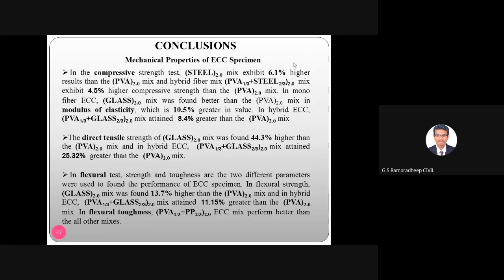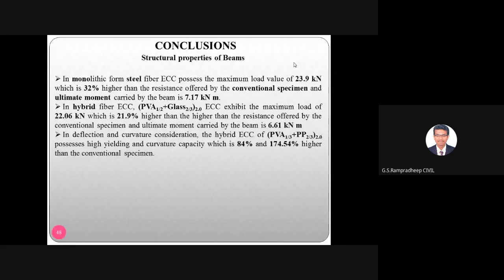And in the compressive strength test, steel gives 6% higher results than PVA, and the hybrid mix with PVA 1/3, 33%, and steel 2/3 shows 4.5% higher compressive strength than the PVA mix. And you can get the modulus of elasticity values with respect to PVA as well as PVA plus glass. Also for direct tensile strength, the mixture was found to be 44% higher in strength than PVA, and PVA plus glass shows greater than 25% over PVA. So they are obtaining better results with PVA and glass, and comparing with the low modulus PVA fiber. And this is for hybrid fiber analysis.